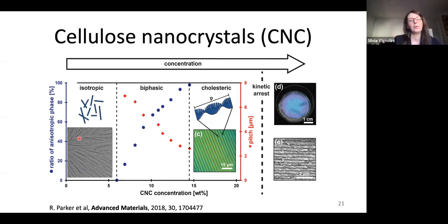And magically, if they are in the right condition, when you put them in a water suspension, so simply having them in water, they start to interact. As you increase the concentration, they start to form what we call a liquid crystal cholesteric phase. You might have heard about liquid crystal displays, and you know that somehow they have to do with color. This is an analogue, from a natural point of view, of a liquid crystalline molecule. Instead of having molecules, now we have colloidal particles.